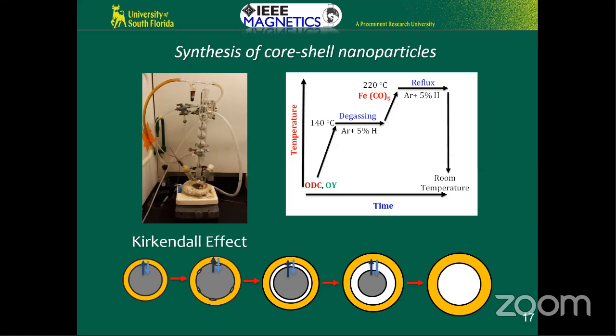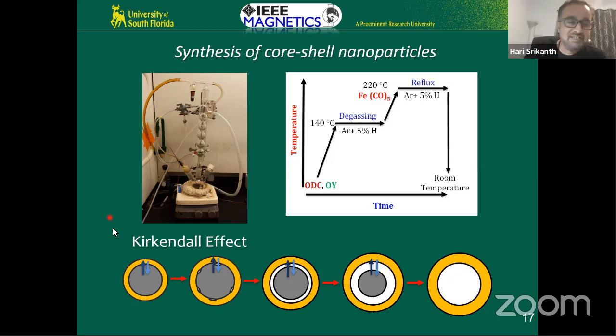Mostly that you see. But the early metallurgists, they actually faced this problem, because if you take a metal particle and insulating oxide, it turns out that because of the differential diffusion of the metal ion in comparison with the oxygen ion, there is an instability at the interface. And because of the instability, you see voids, holes opening up. And these voids get bigger and bigger. And ultimately what happens is that the metal inside oxidizes, the shell becomes thicker. So you end up with a hollow nanoparticle. And this happens as a function of time. You don't have any control over it.